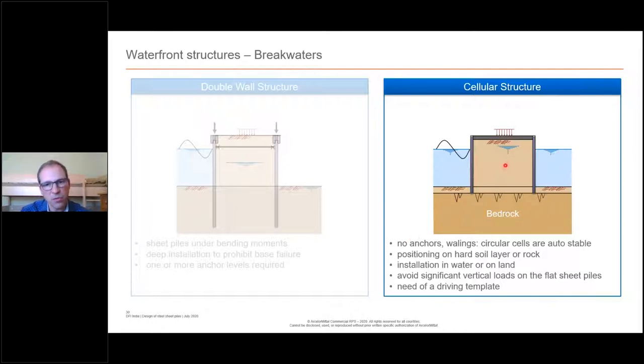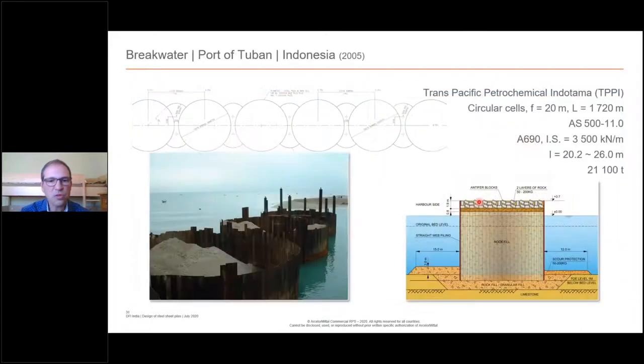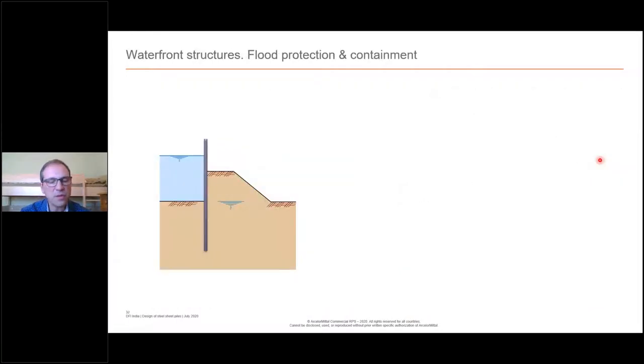You have to backfill with a good soil, so granular soil. But as I already said, you don't need to penetrate into the soil so much. And if you have the bedrock, which is quite shallow, it's also a quite good solution. So one example in Indonesia, where they built a 1.7 kilometer long breakwater with circular cells with a diameter of about 20 meters. As I said, up to 25, 30 meters is the maximum diameter that can be achieved. And the sheet piles were up to 26 meters long, which is already quite a long length for this type of structure because the sheet piles don't have any stiffness.